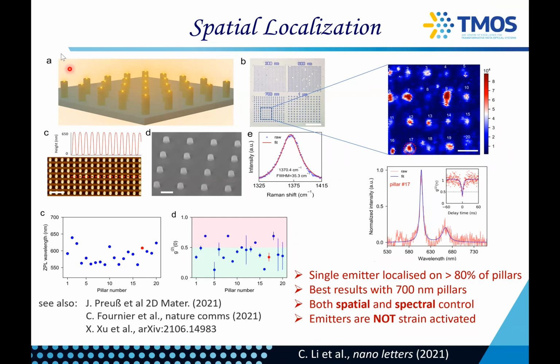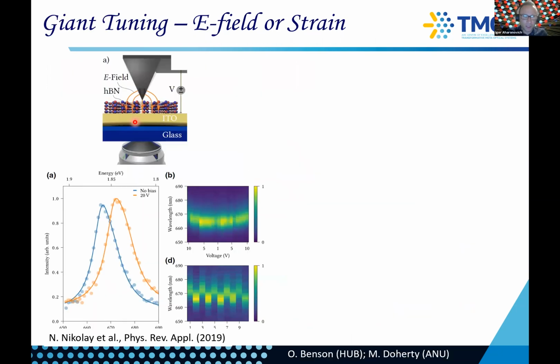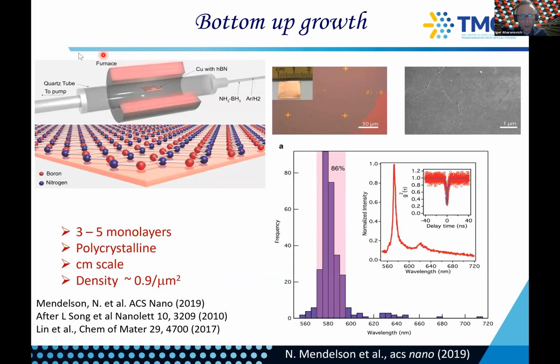And how do you grow the hBN without a catalyst here? This is a question that we have been asked maybe five times during the review process, and now once again, and the answer is we don't know. Of course, with copper, it's very easy. You catalyze, and there's a decomposition, very well established in the literature. Without the catalyst on the dielectric, we don't know why, but it works. And you use the same precursors that you would use for copper? Exactly the same, and the temperature is a little bit higher, maybe by 100 degrees or so, but overall everything is exactly the same.